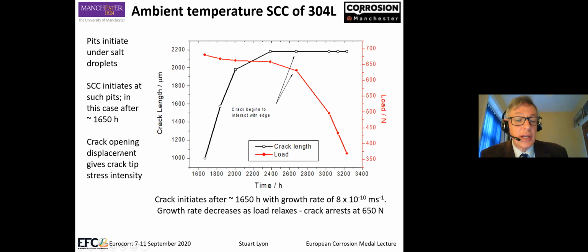And by measuring the linear displacements using this digital image correlation, we can get a crack opening displacement, which we can turn into a crack tip stress intensity factor. So in this particular analysis, we can calculate the load from the unloading curve on the proving ring. And the crack initiates, as said, after about 10 weeks, with a crack growth rate of about 8 times 10 to the minus 10 meters per second. And the crack growth rate decreases as the load relaxes, and the crack arrests at 650 newtons. This is not a constant load experiment because of the nature of the proving ring.